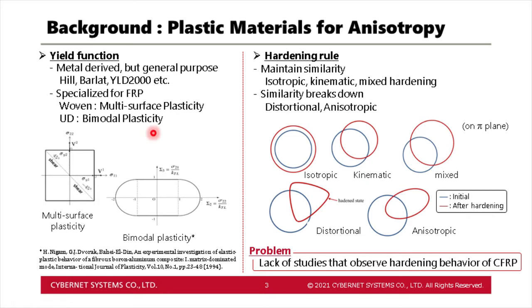Bimodal plasticity theory has been proposed for the UD composite, that is the concept of our study. On the other hand, hardening rules have also been proposed in a wide variety of models. This figure shows a schematic of the yield surface before and after hardening, drawn on the pi plane. The 3 in the upper row move or expand while maintaining the similarity of the initial shape. The 2 hardening rules in the bottom row collapse the shape of the yield surface. In this case, the initial surface is restricted to be isotropic. It cannot be applied to the problem of anisotropic yield surface. Above all, there are not many examples where the hardening behavior of UD composite has been accurately observed.